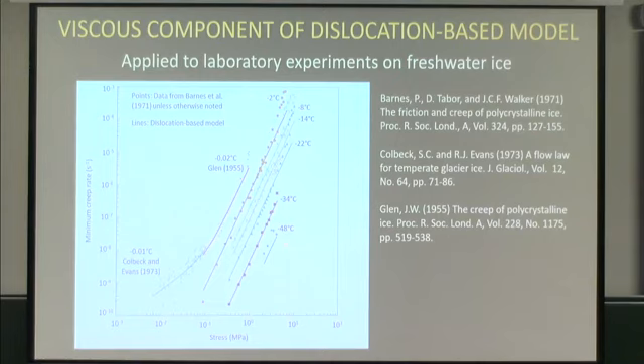And when you put in this factor I've applied to the dislocation density as a function of temperature, it really captures a little bit dodgy at -48 here, but -34 right on through, I think it does a bang-up job capturing this temperature effect and the stress level effect.